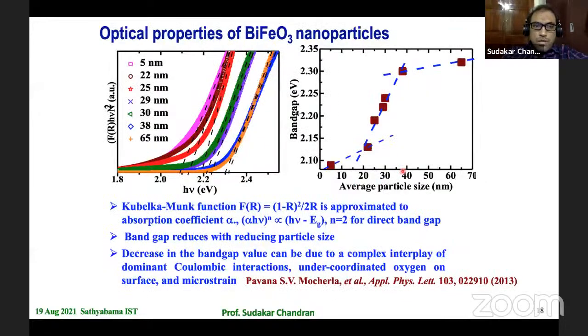And this has an influence on the optical properties, specifically the band gap structure that we have studied shows that around 20-30 nanometer, there is a sudden decrease in the band gap value. Which means, we can control the band gap by tailoring these defects. That's the message we get from this first set of studies that we did at a very early stage. This is the work which we published long back in Applied Physics Letters.